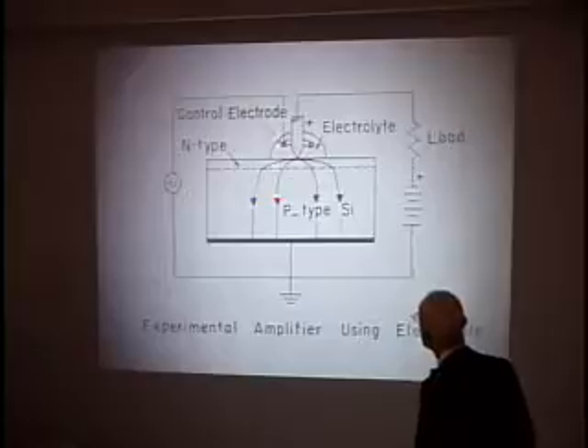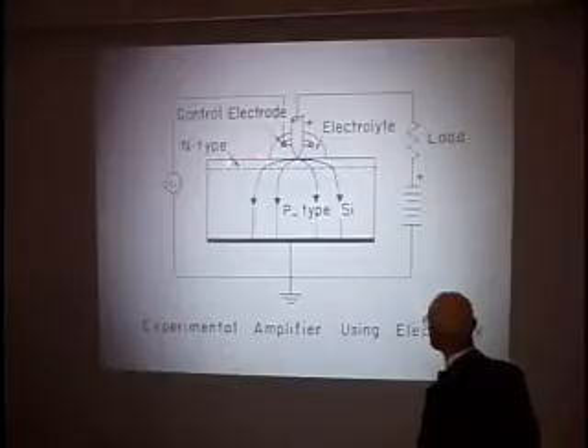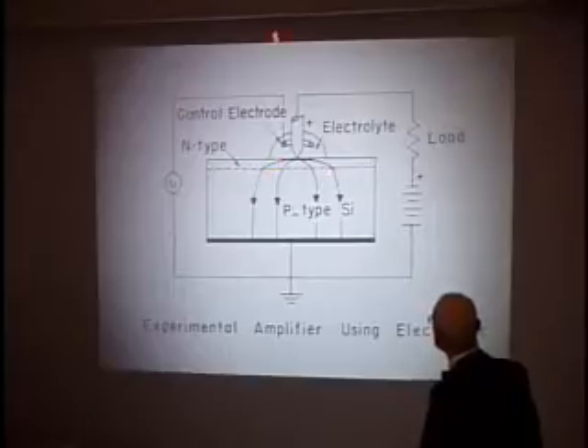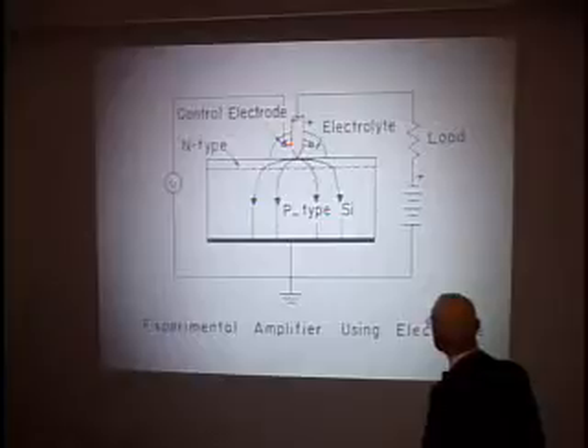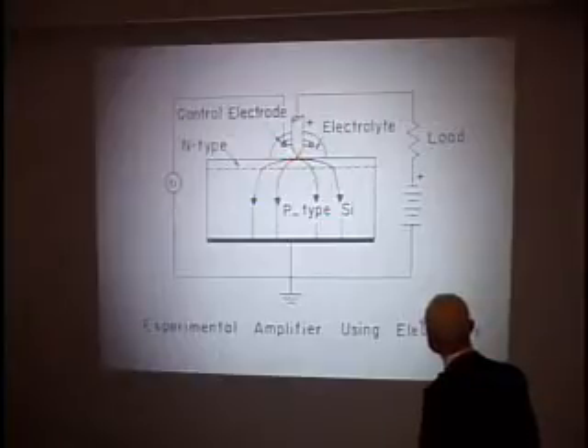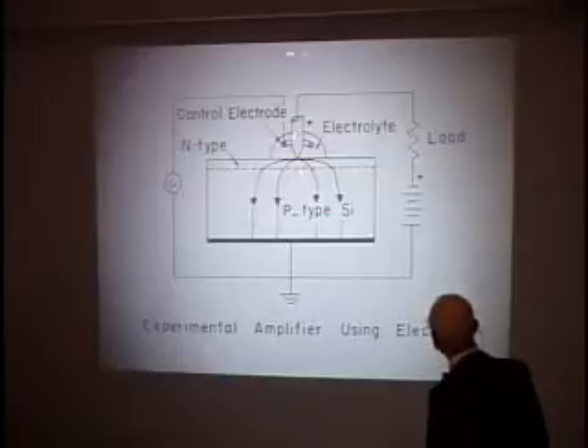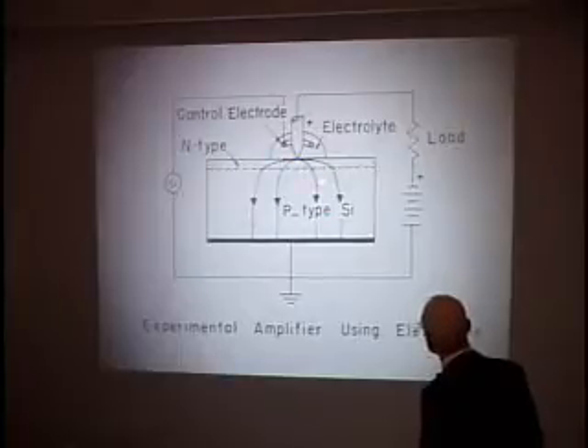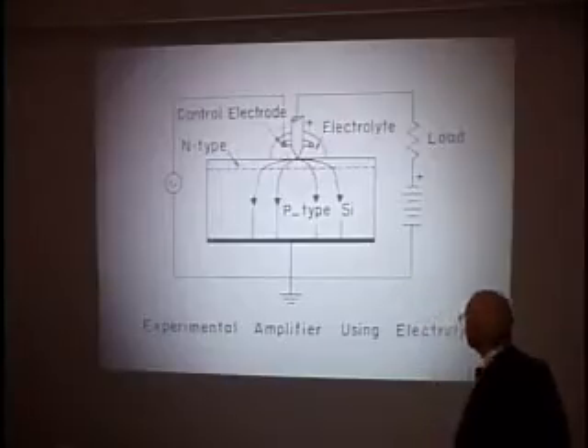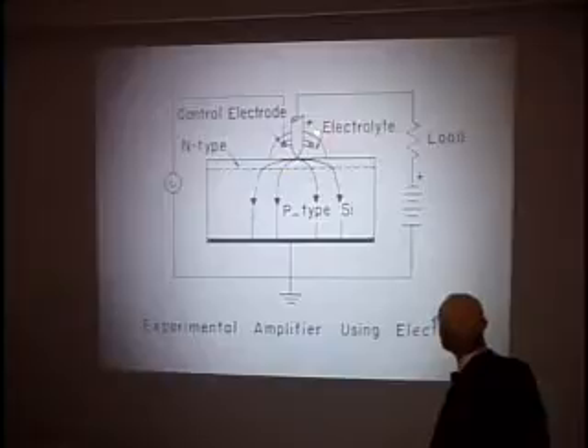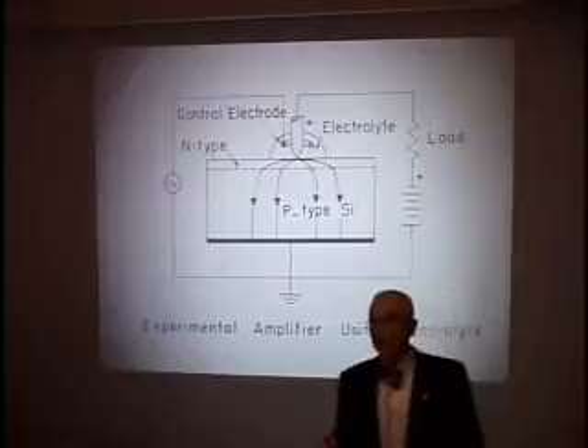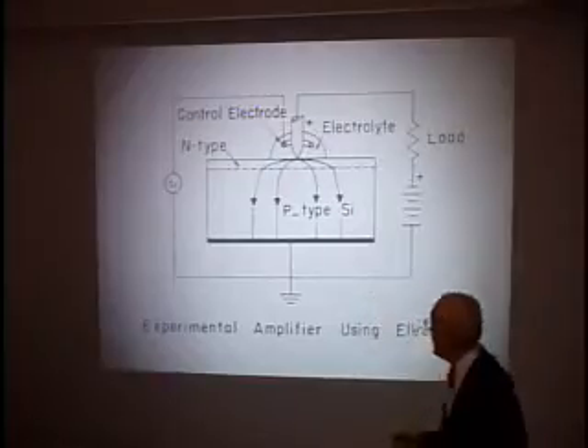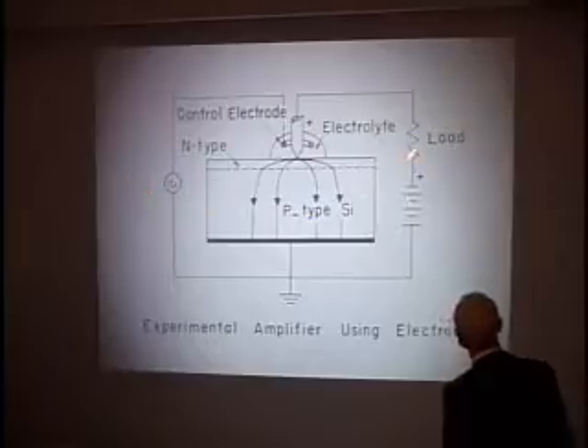He and Walter Brattain had done the following experiment. John was a master in understanding the surface, and he knew that there was an inversion layer on this surface of silicon. There's an N-type layer here, an inversion layer, a channel, and they put down a point probe here that is insulated, and the point contacts are here, and there's a spreading resistance here. When electrons are extracted up this way, and they're flowing in there, there's a radial resistance here, and they put an electrolyte here, and when they modulated the voltage on the electrolyte, that modulated the conductance of the surface layer and modulated the behavior of the device. In other words, a signal here resulted in an output signal here.